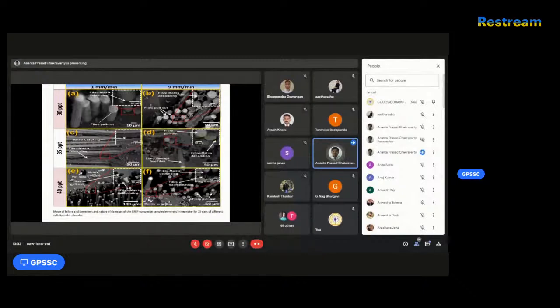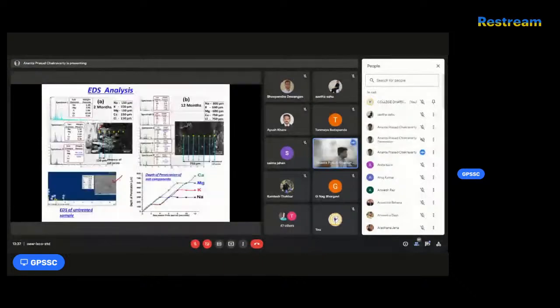to cause the creation of this organic compound inside it. So when we go for EDS analysis from the surface to in depth, point EDS is captured at certain points, and with respect to that scale I have measured up to what depth the significant EDS peaks appear, and we can visualize the extent of penetration of the salt components, in reference to the EDS of the untreated sample.